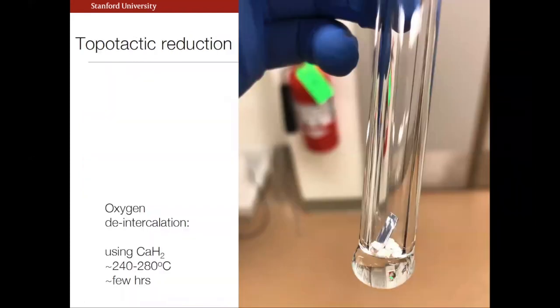And so we're going to merge these two together, which is sometimes hard to visualize. I just wanted a picture of this rather expensive and elaborate MBE or UHV chamber. And this is the most important step. You're looking at a glass tube. This is a 2.5 by 5 millimeter slice of our thin film, loosely wrapped in aluminum foil. These little rocks are calcium hydride. We vacuum seal the whole thing and anneal it at fairly low temperatures to induce this oxygen deintercalation reaction.